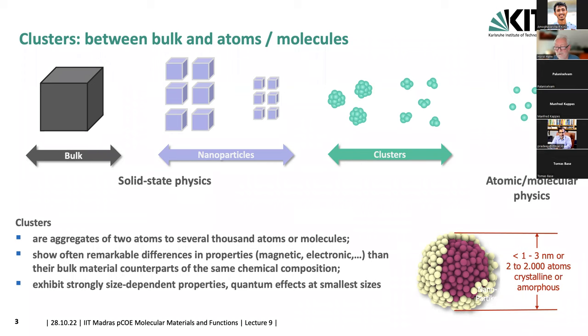So a cluster, which is shown here, is a result of an MD, a molecular dynamics simulation of an amorphous cluster, which contains a few hundred atoms of two different elements, in this case, nickel or copper zirconium. And these are in the size range of 1 to 3 nanometers, which is still distinctly larger than the clusters, for example, which you call atomically precise.